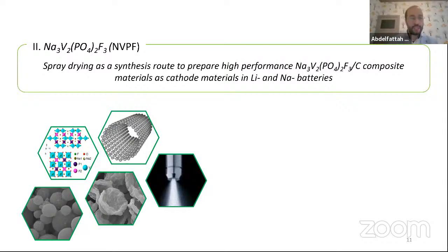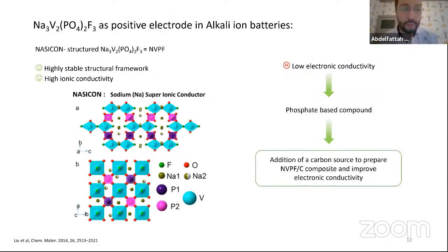Here I will give a presentation on sodium vanadium fluorophosphate, NVPF material, one of the most promising cathode materials for sodium-ion batteries. For example, in France, Tiamat has already started to use it for commercial application. Why is this material one of the best? Because it has a very stable structure framework. It has very high ionic conductivity thanks to its structure, and also a very high theoretical capacity, because we can extract either 2 or even 3 sodium, and by that we can reach a very high capacity.